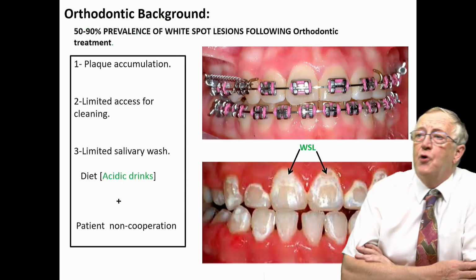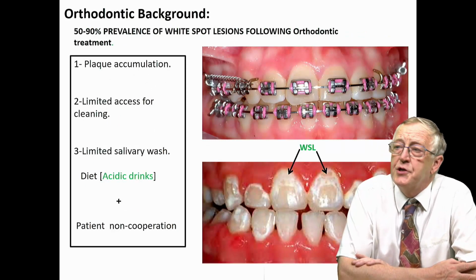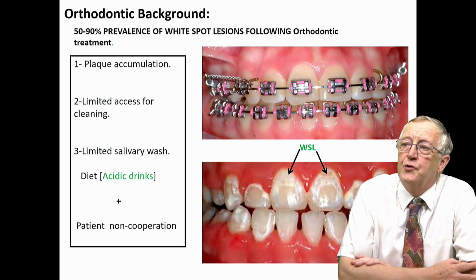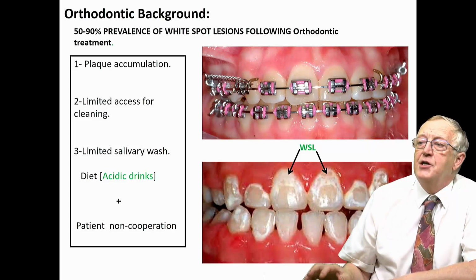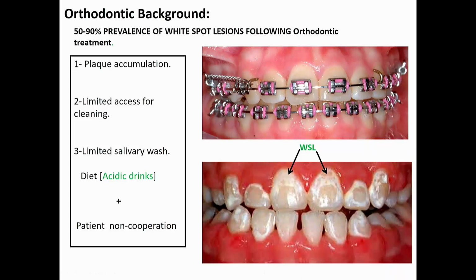So this is the big problem in orthodontics, that after fixed bracket orthodontic treatment, the patient's often left with this white discoloration as a result of white spot lesion formation on the tooth surface. And this is because it's difficult to clean and brush around the brackets, and plaque tends to concentrate in the gaps and the crevices around the brackets, resulting in demineralization of the enamel.